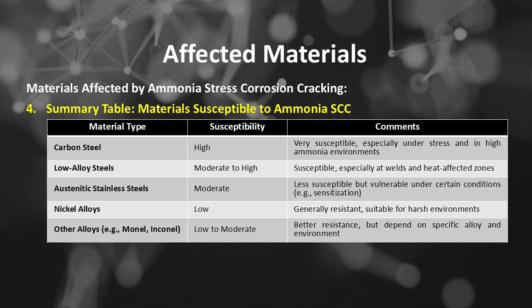Number 2 is low alloy steels. It has moderate to high susceptibility. The susceptibility increases at welds and heat-affected zones. These areas are stress concentrators, making them weak points. Its implication is that it requires strict welding quality control and inspection.